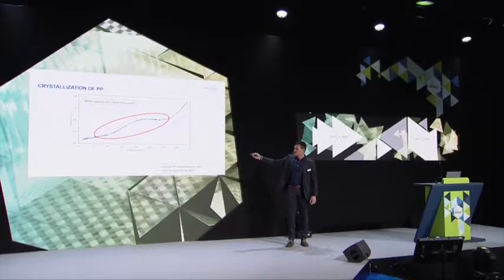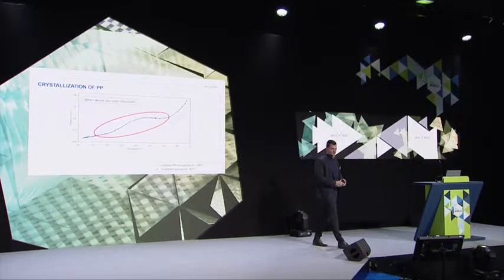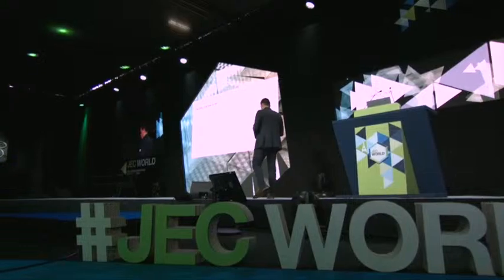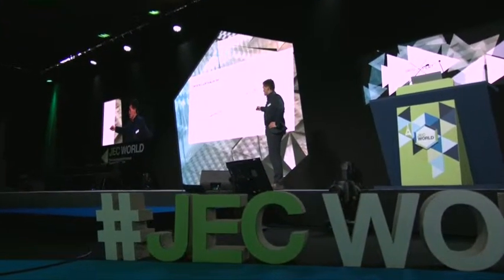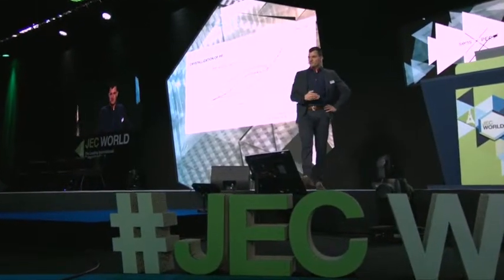The big question is, when would you open the mold to avoid residual stresses, warpage afterwards, and to keep dimensional stability of this part? What you can see, if you follow from the right to the left, this peak here is the solidification process of polypropylene. Crystallization and the freezing process of polypropylene. The best case would be to demold here, where we have a linear behavior. But in terms of shorter cycle times, cost reduction, energy reduction, I have to find a balance between stability and mechanical performance. A little bit of warpage I can deal with, so I can find a spot anywhere here where most of the crystallization has already finished, but I can find the balance between process efficiency and material behavior and stability in this case.